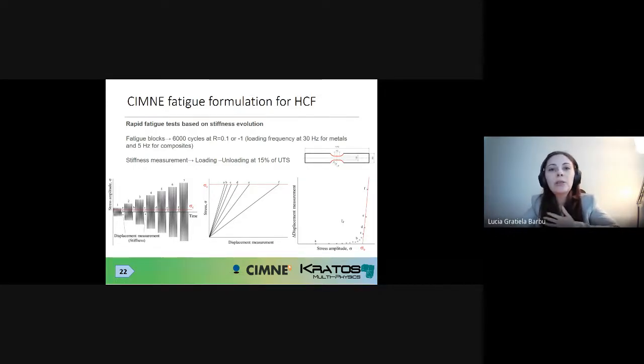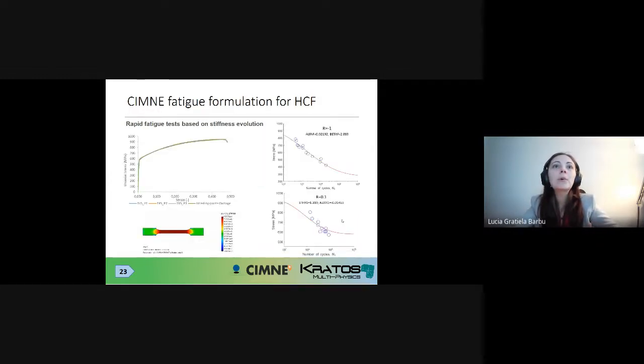And for us, when they developed these experimental techniques, it was interesting to see if our model, our formulation for high cycle fatigue, was capable of giving accurate results for this type of test also. And we began to do a calibration. It's specific for a TWIP steel. We began, as you do in a numerical simulation, by calibrating the static parameters from the engineering stress strain curve. You can see here the experimental curve, and it's a very good adjustment with the numerical curve that we obtained when we calibrated our model parameters.